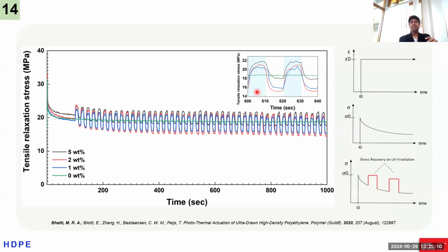the only difference between these two is the concentration of crystalline and amorphous regions. So crystallinity increases as soon as we increase the draw ratio. But at any point, the crystalline regions, the lamellae, are interconnected with the tie molecules, which are elongated amorphous regions. So when we illuminate the polymers with the light and heat is generated, these tie molecules tend to contract because of the negative thermal expansion coefficient. And these are entropy-driven conformations. So when we remove the light source, because of the entropy, they tend to get back to their original state, because the crystalline regions on top and bottom are at the same position. So the entropy tends to get them back to their original position.